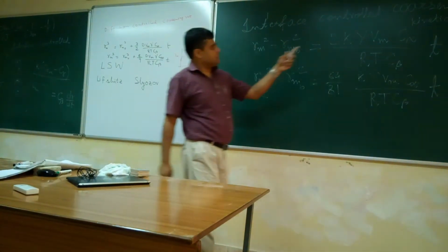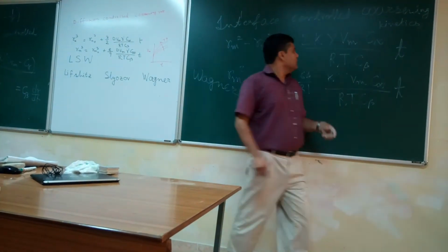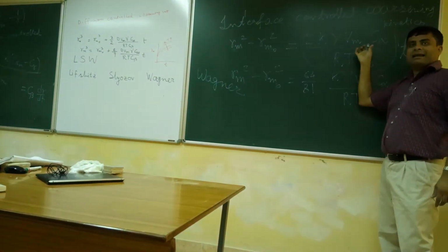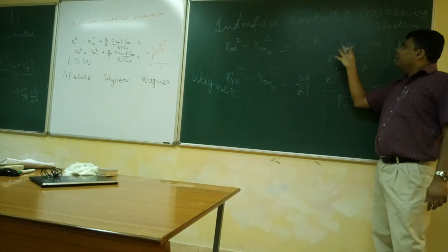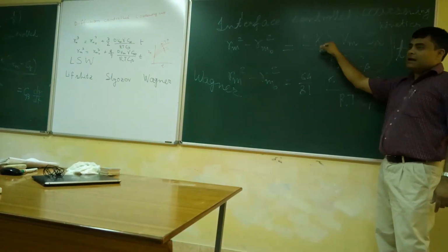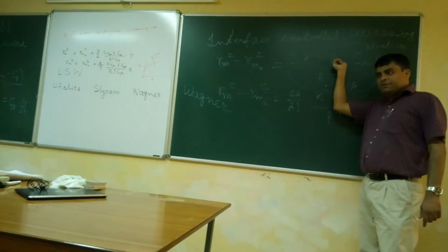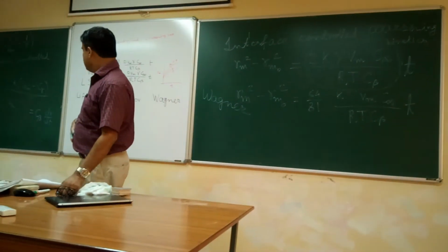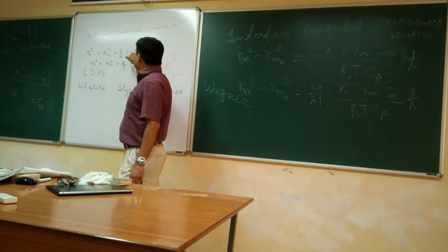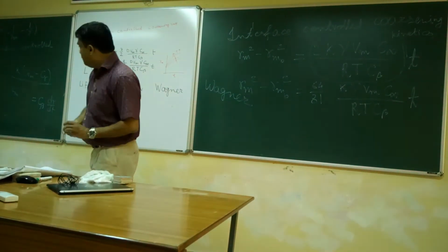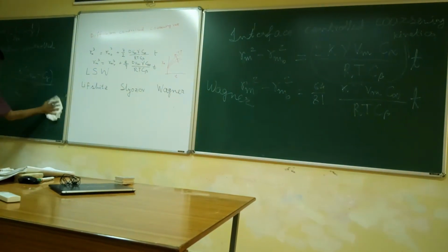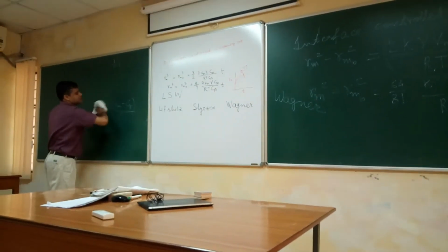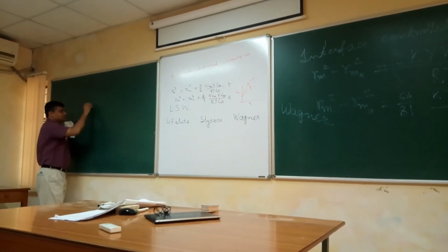Here also gamma is up there in the rate constant, which is proportional to your C alpha and gamma, but there is no diffusivity term here. Here also gamma C infinity D. So if you have to design an alloy which you do not want to partition during service, you have to play with these things.